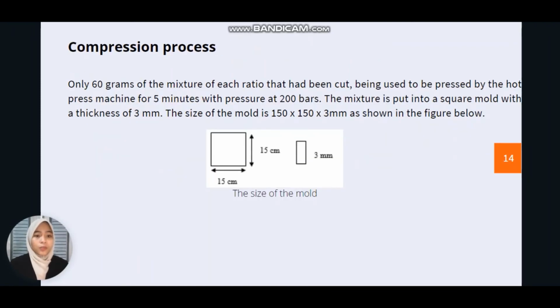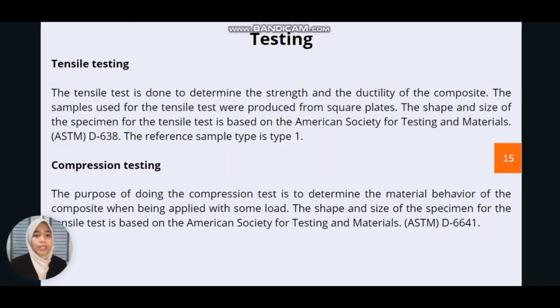And then for the compression process, only 60 grams of the mixture produced for each ratio will be compressed by the hot press machine for 5 minutes with a pressure of 200 bar at 200 degrees Celsius. So the mixture will be put into the square mold. The figure shows the dimension of the square mold, which is 15 centimeters in height and length and 3 millimeters in thickness. Next, testing.